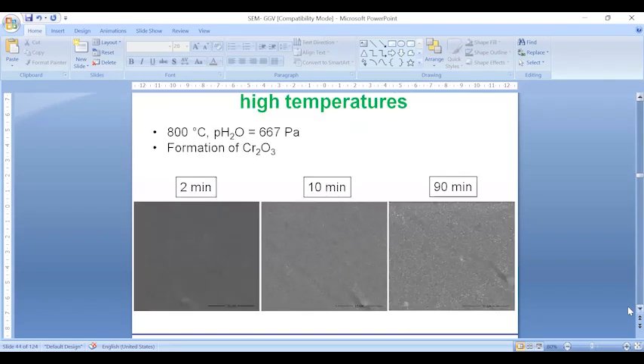This is one of the chromium oxide samples that you can see here at 800 degrees centigrade temperature at different times. Here we can find out, if you put your sample at, that is called handling the sample, or any type of processing system at a different atmosphere, different temperature, different pressure, you can see how the system will nucleate with respect to your times.